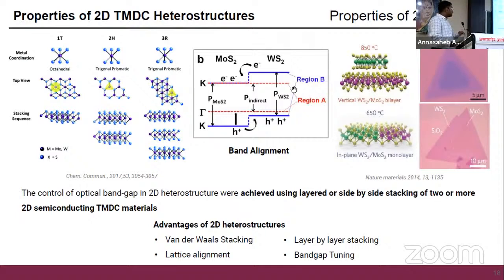The main thing you need to understand is the van der Waals nature of these 2D materials. Because of these van der Waals forces, we can stack them on each other and separate them from each other easily. Since this arrangement is the same along other materials, it is easy to align them on top of each other, because the band structure will also change upon the orientation of the top and bottom layer. That's why there is a need for lattice alignment also. Plus, we can also do layer by layer stacking by selectively growing, such as from one material to another, then a third, or again the first material.